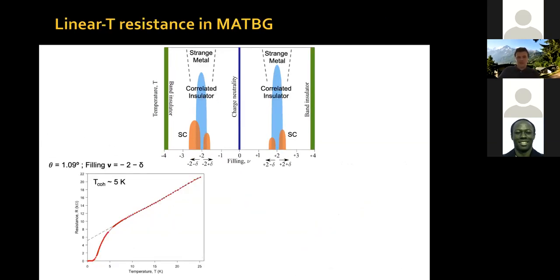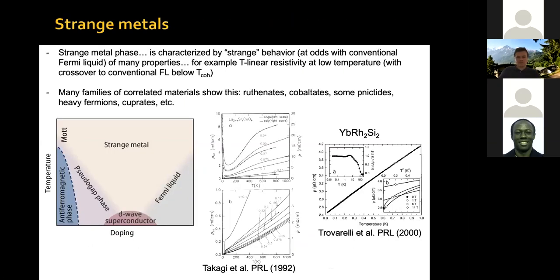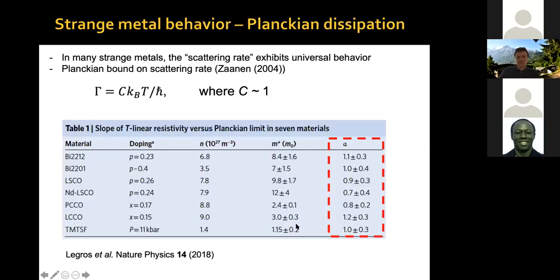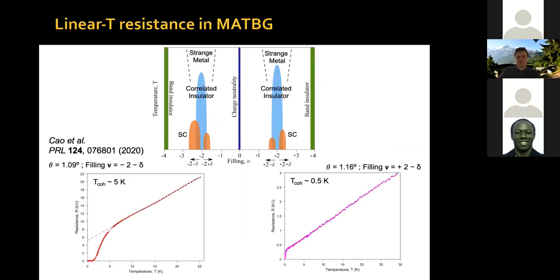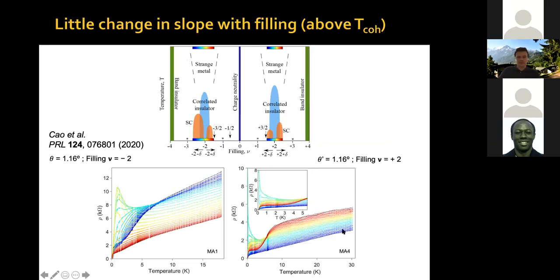The curves that I show in this diagram are for different materials, different crystals. We can do this exact same thing continuously as a function of density in the same device. Okay? This is for 2 different devices, continuously as a function of density from the same device. You can see that at low temperatures, superconductivity takes place, correlated insulator behavior, all kinds of things happen, but above a certain temperature of the order of 5 Kelvin or so, you have this linear behavior, and the slope doesn't change dramatically as a function of density. Okay, the slope is very similar.